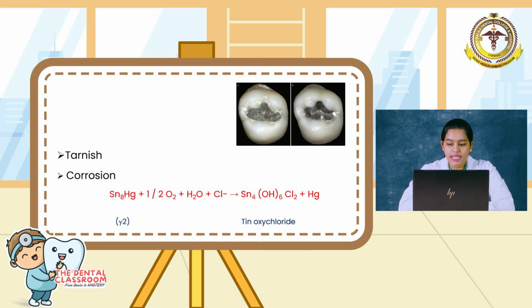While corrosion is the chemical or electrochemical reaction of a metal with its environment and its progressive destruction by formation of corrosive byproducts. Gamma 2 phase is responsible for corrosion in case of low copper amalgam. This phase reacts with oxygen, water and chloride to form tin oxychloride, and mercury is also released during the reaction. This released mercury then reacts with the unreacted gamma particles and produces additional gamma 1 and gamma 2 phases, resulting in more expansion, which is termed as mercuroscopic expansion. This additional reaction and expansion result in porosity and reduction in strength of the restorative material.